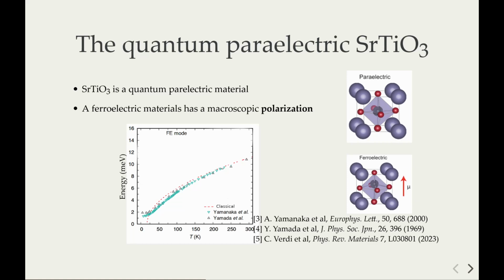So there are multiple ways to stabilize a ferroelectric state in strontium titanate. One of these is strain. Another one is oxygen mass substitution - if we replace oxygen with a heavier isotope, it does go into a ferroelectric state.